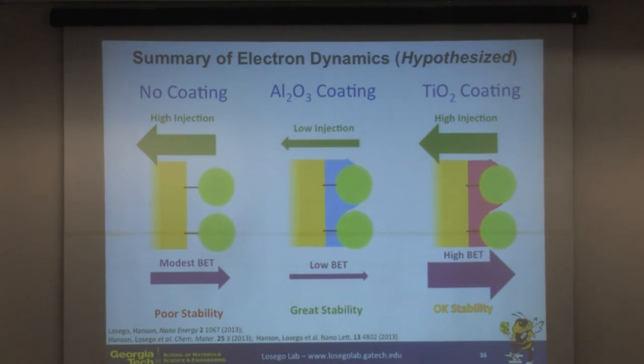So without a coating, we know that there's high injection that occurs, and there's some back electron transfer. So we want mostly injection. We want it to be collected by the device. We don't want the electrons to come back into the dye. But in fact, even for a standard device, we actually have more injection. The injection is even faster than we need it to be. So we could take a bit of a hit to injection and still have a high performing device.